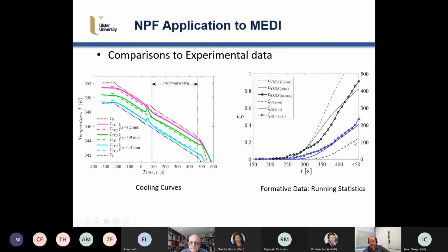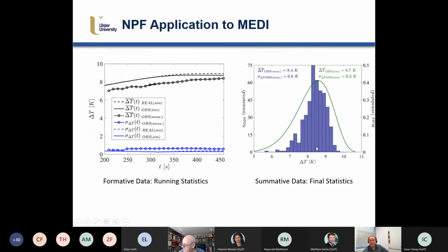So we're able to gather this information from the model, and in particular, the latent heat is driven by the volume fraction. So you may say we couldn't observe directly or compare, confirm or validate directly the volume fraction, but the volume fraction informs the thermal model and drives the latent heat. So since we have thermal agreement, we should be quite close on the volume fraction as well. Some more statistics here. We have average undercooling that was observed and modeled. And you see that the average undercooling was around 7, and it increased up to around 8. And so you see the simulated in the solid line, and also the standard deviation. The standard deviation tended to reduce. And there was a slight increase here measured, but generally the trend was a decreasing trend, and that was captured in the model as well.